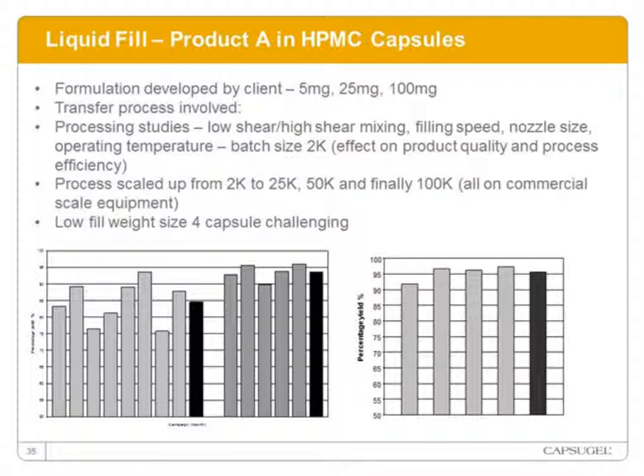And this is a particularly challenging product because of the low capsule size and low fill weight, particularly for the banding process here with capsule transfers across the banding machine. But you can see that across 3 campaigns, there was a lot of banding development work being conducted in the first campaign across 8 batches, with an overall yield of just over 70%. But as we increase and modify the processing as we moved across the campaigns, we're eventually up to yields of an average of over 95%, which is very good for this particular process.